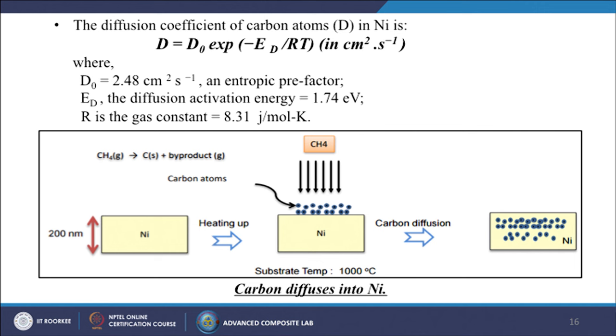So, this is the whole schematic diagram of how we are forming the graphene. We have nickel, which has a 200 nanometer thickness. We heat that material, then we purge the methane gas inside the chamber. When this methane gas comes in contact with the nickel, it forms carbon atoms on the substrate itself, then these carbon atoms go inside the nickel wafer.